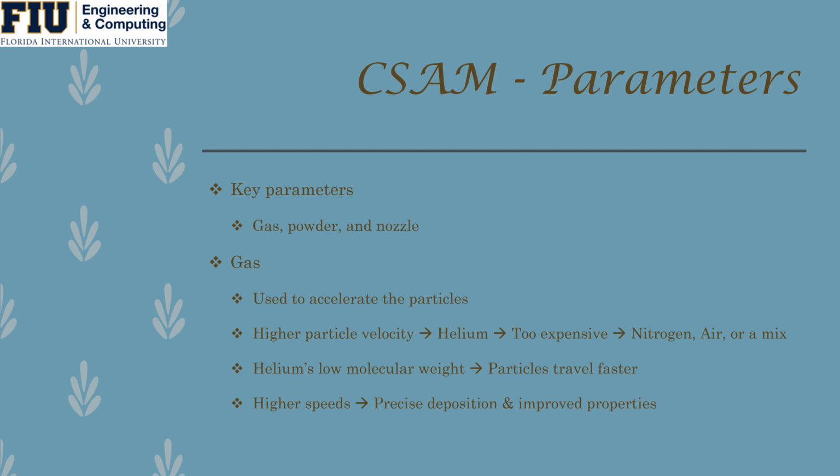This gas is used to accelerate the particles, as mentioned before, supersonically. In order to achieve a high particle velocity, helium is ideally used. Since helium is very expensive for production runs, nitrogen, air, or a mix is used instead. The reason helium is ideally used is due to its low molecular weight, thus allowing particles to travel faster. By having high particle speeds, it allows for precise deposition and improved overall properties.